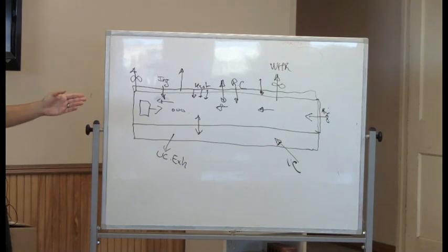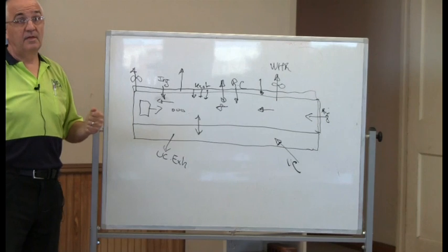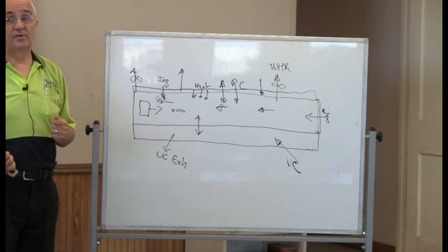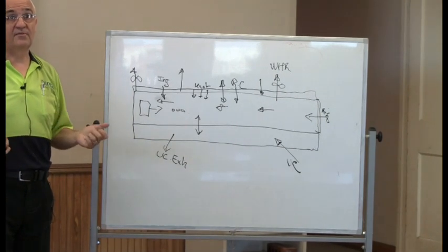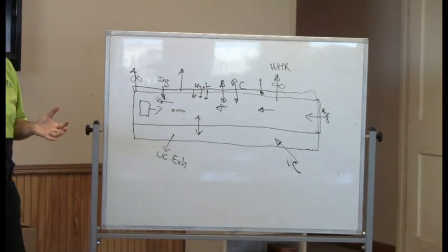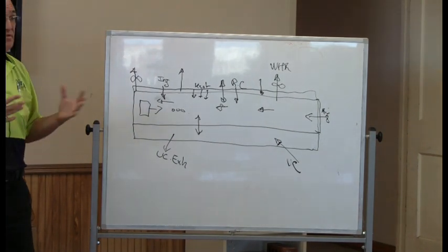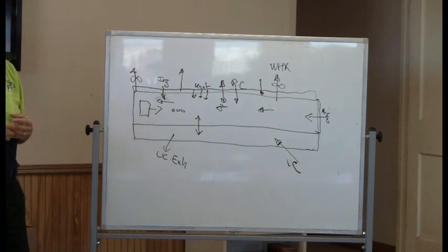A lot of the time, people tend to play with excess air because, oh yeah, I'm going to drop the flame temperature. But a lot of the time, especially in the firing zone, you should not have to drop the flame temperature because you need that temperature, but you need the air to actually distribute that energy and temperature properly. Okay?